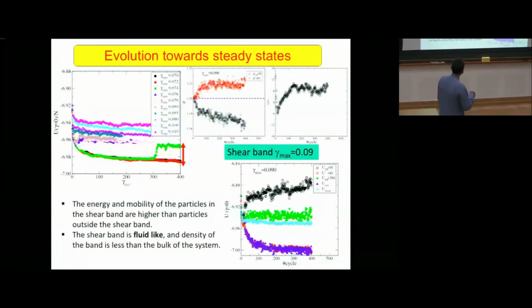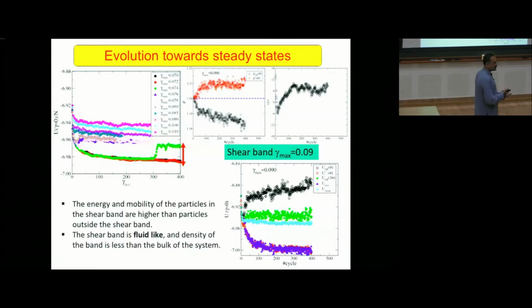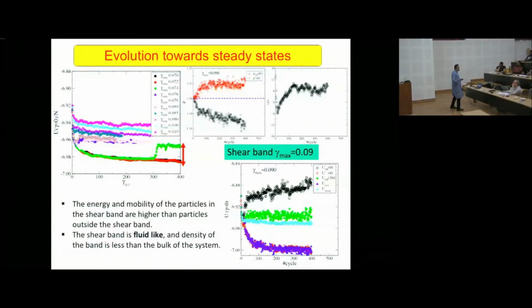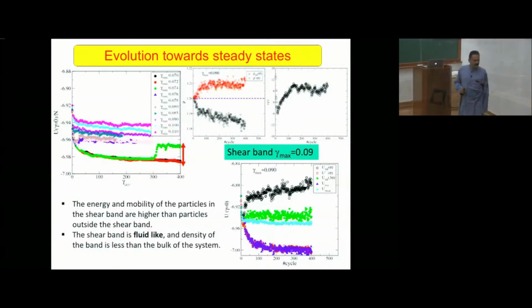And so there are some other interesting features. One is that the shear bands actually move around in the course of your simulation. Something that's unexpected, at least by me, was that if you look at the density of the system inside and outside the shear band, there's a bifurcation. So the density of the material becomes smaller and smaller inside the shear band as time goes on.